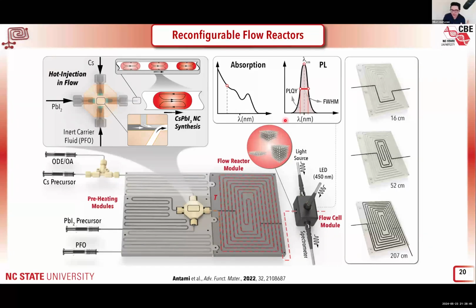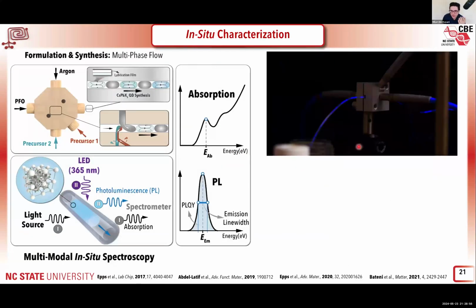And then the reactor plate is designed in a way that we can accommodate different reactor volumes within the same plate, so we don't need to redesign or remachine this heating plate. In situ spectroscopy, as I mentioned briefly, we have these bespoke flow cells. This is a stationary one that we attach to the end of the reactor, where you have your tubing going through this flow cell, and the product that is inside these blue droplets leaving the reactor goes through this flow cell, and we can do UV near-infrared absorption or photoluminescence spectroscopy.